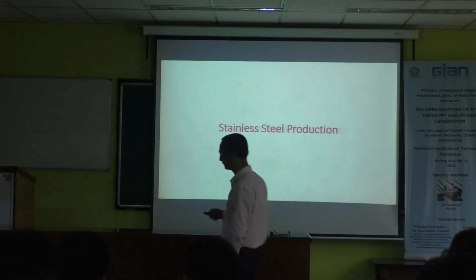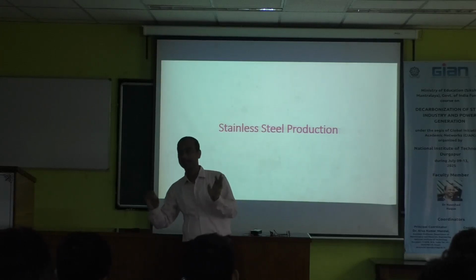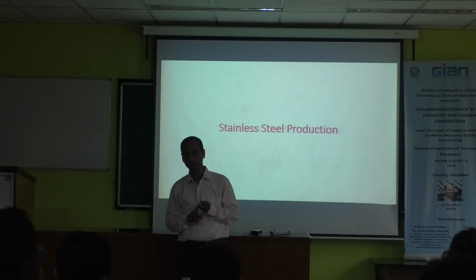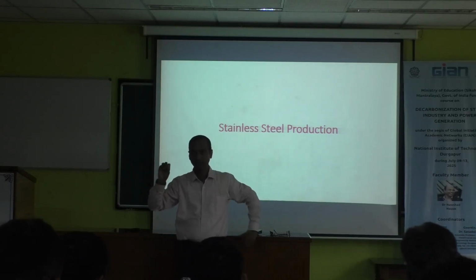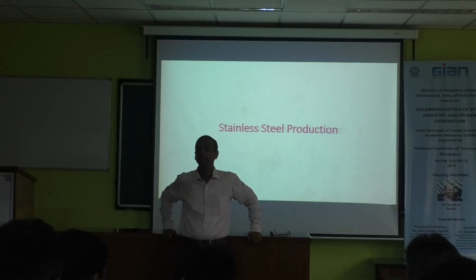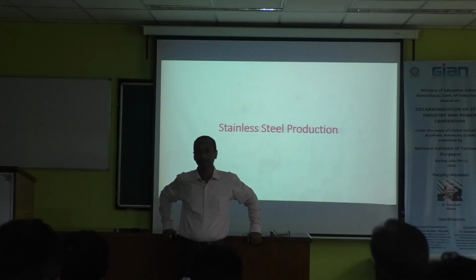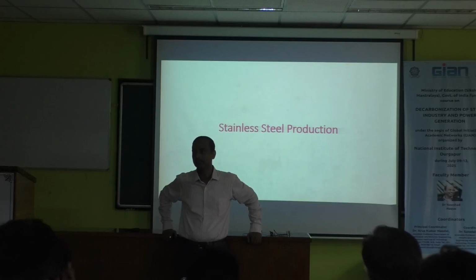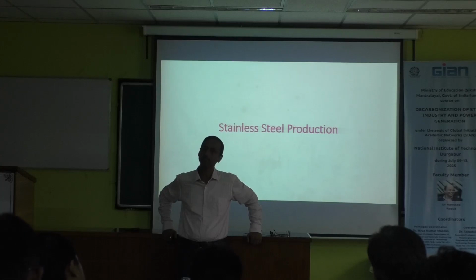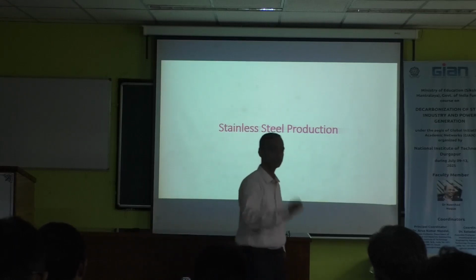Stainless steel production requires, if you see, normal stainless steel needs chromium, and for making the steel, it requires a very low amount of carbon percent. So conventionally, how is it prepared? Low carbon ferrochrome is required. This ferrochrome is an alloy element which is used to get the chromium content in the steel. But low carbon ferrochrome is required, otherwise the stainless steel grade will be high carbon and it will not give you the stainless property.